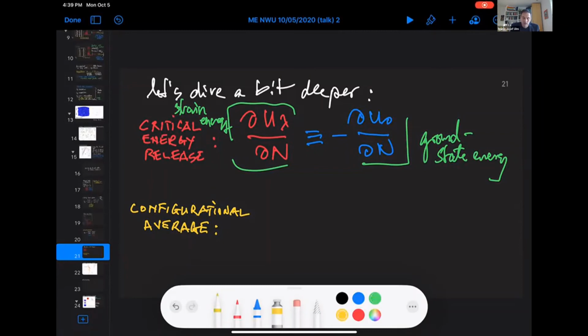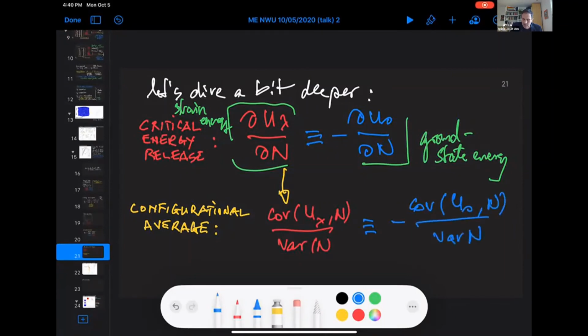Now, the only thing we do now is we don't take the derivatives, but we evaluate this from the configurational average, in terms of the covariance of U_lambda and N over the variance of N, which is equal to minus the covariance of U_0 and N over the variance of N. And you may ask yourself, why is that negative? Please remind yourself that U_0 for a homogeneous material is basically just N, the number of bonds, times epsilon_0 with a negative sign, because epsilon_0 is negative. From the plot, you remember this energy U versus R, you see that's the epsilon_0. So it has a negative value, which is where the sign comes in.